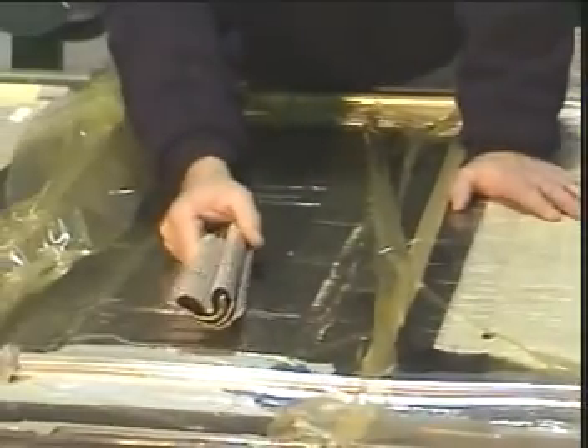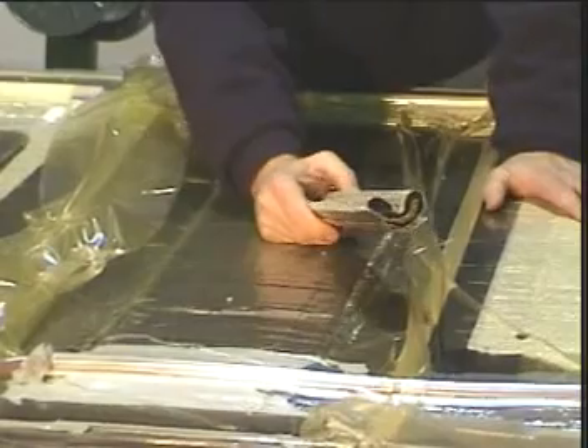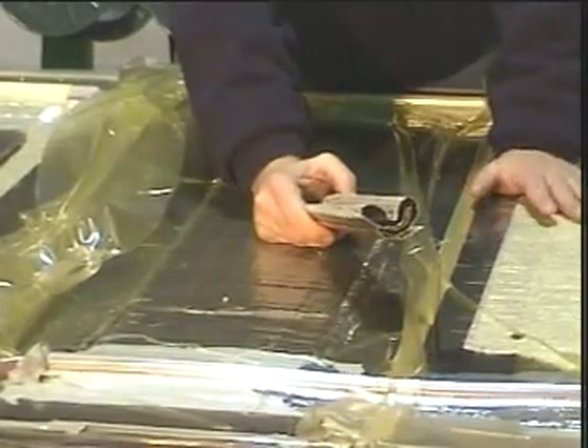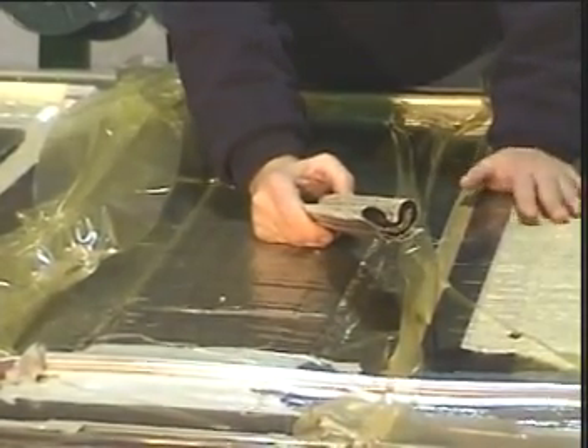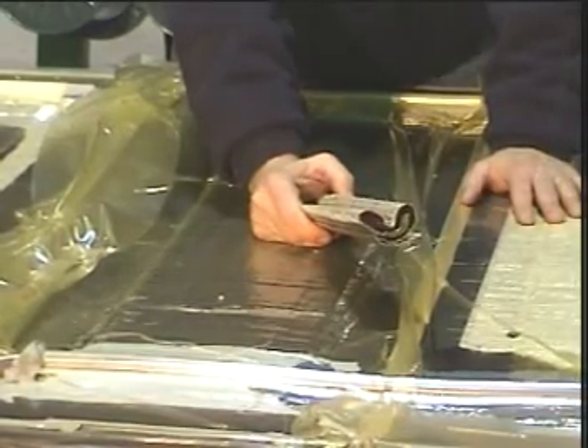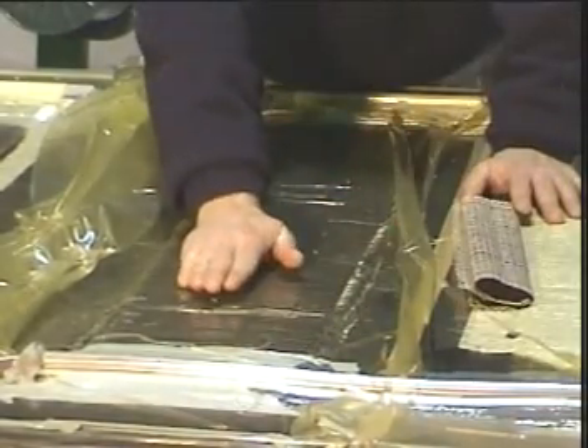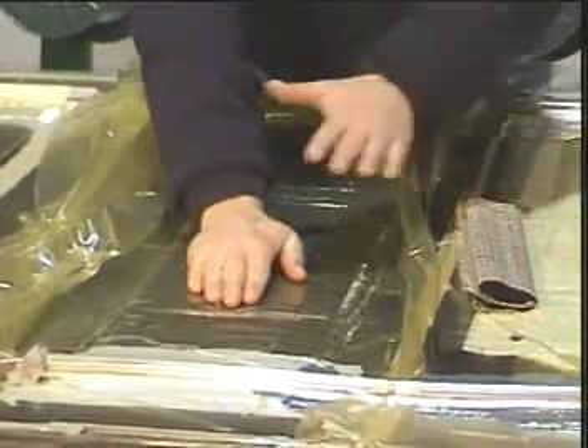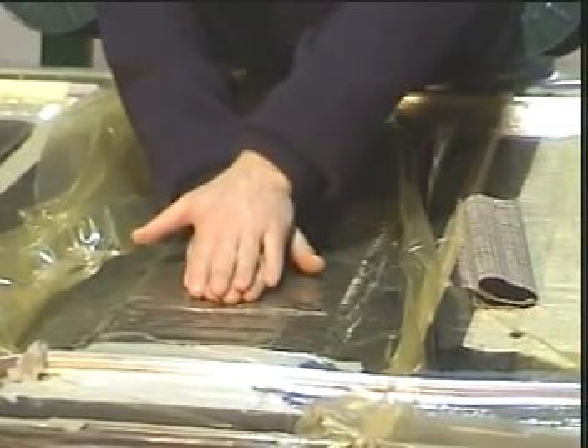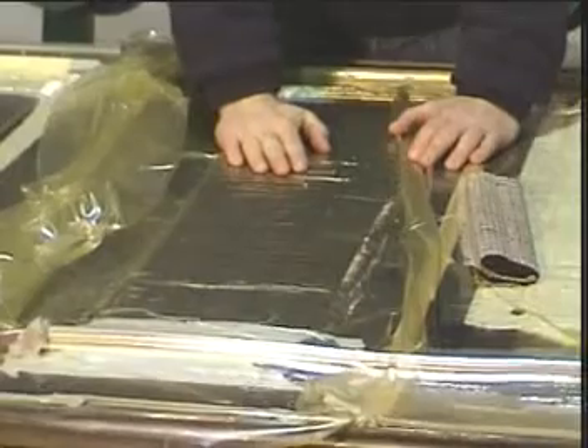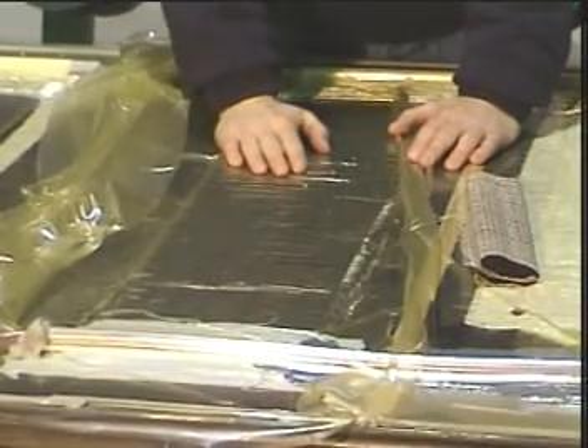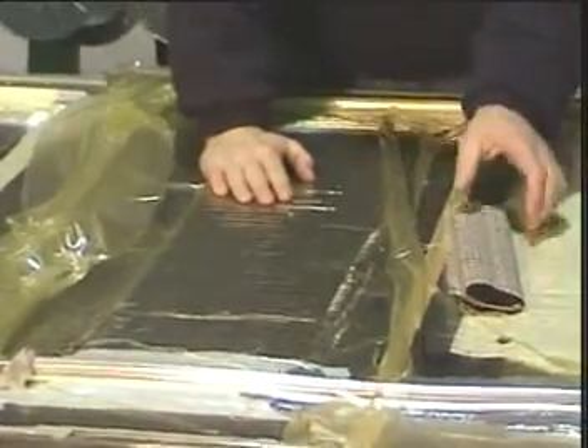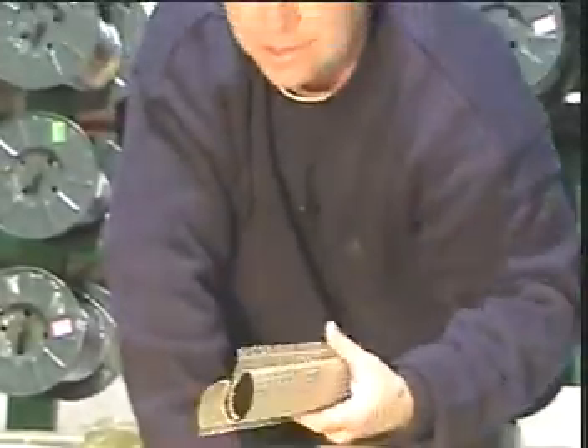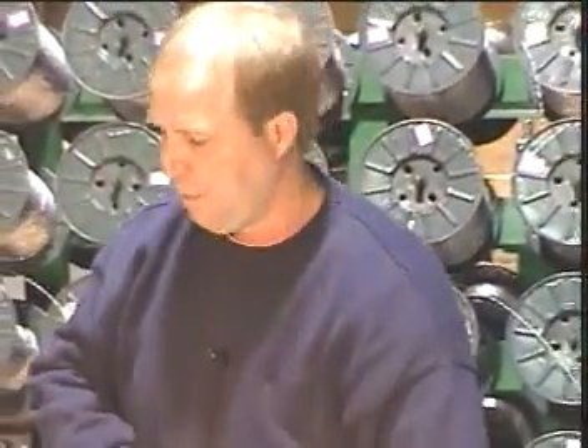In the carbon part, again, it never ceases to amaze me. When you take carbon fiber with vinyl ester resin, it acts almost like a sheet of plastic. The fibers are so small in the carbon, they're just teeny. As they nest together, they create tighter and tighter and tighter packing density, which would be great if you could get resin through it. The problem is you just can't get the resin through it. We haven't even moved a quarter inch into the carbon panel. I believe here we've moved maybe about 2 inches at most into the glass panel.